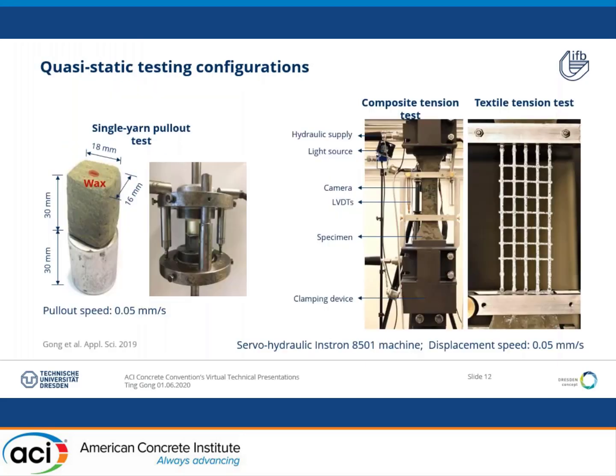Both the pullout test and tension test were performed with a displacement speed of 0.05 mm per second, and the entire length of the composite specimen is 700 mm with a 150 mm gauge length in the middle. Note that the textile specimens were produced in the same way, but with only bare textile structure in the gauge length. Photos were taken every 5 seconds with a high resolution camera for the purpose of digital image correlation.